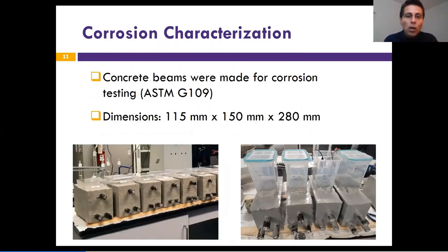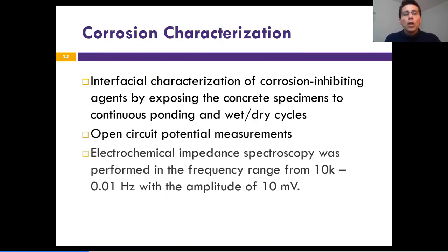And the corrosion characterization. Once we formed the concrete samples, the reinforced concrete, we put these concrete beams in a configuration to test corrosion based on electrochemical methods. You see the containers here on the right bottom part of the slide. We put in a 3.5% salt solution to induce a corrosive environment in the specimens. Based on this setup and the different concentrations of the microcapsules, we did different electrochemical testing, which for corrosion is very classical. We call it open circuit, which I will describe, and electrochemical impedance spectroscopy, which is a non-destructive evaluation technique that is going to be very useful for our characterization of the microcapsules.